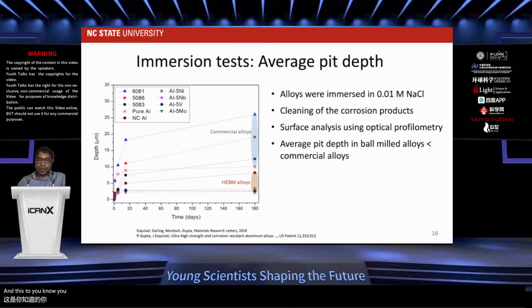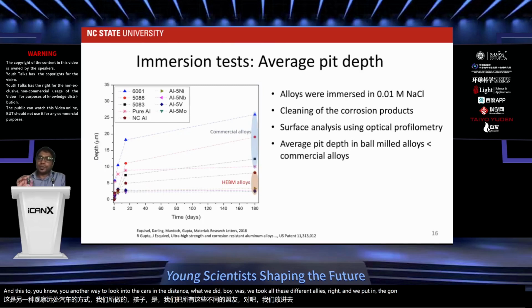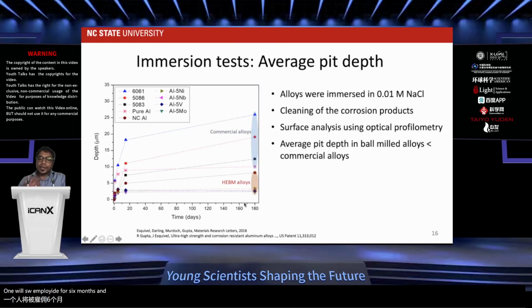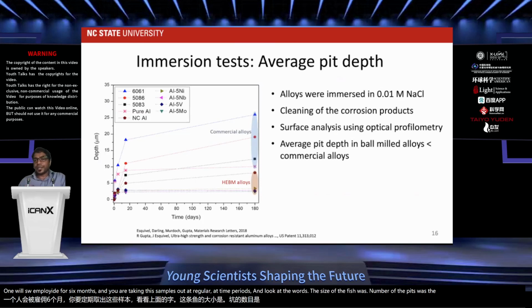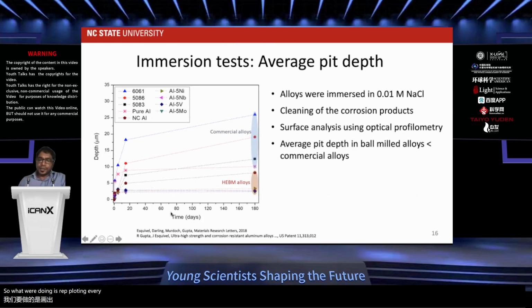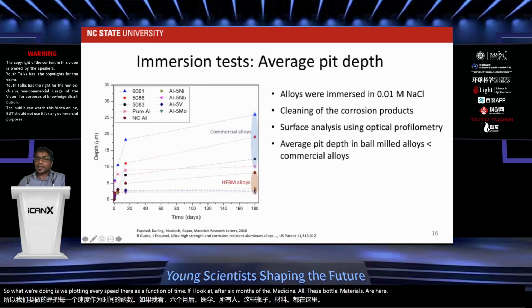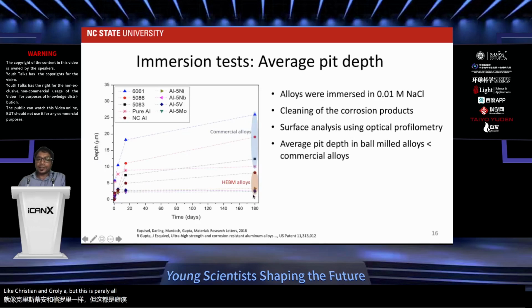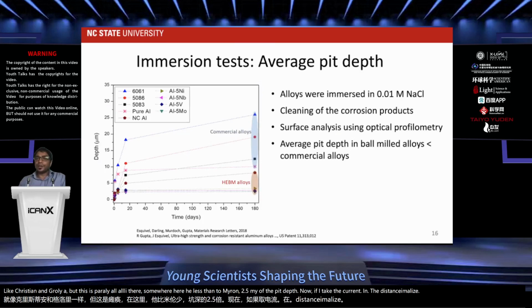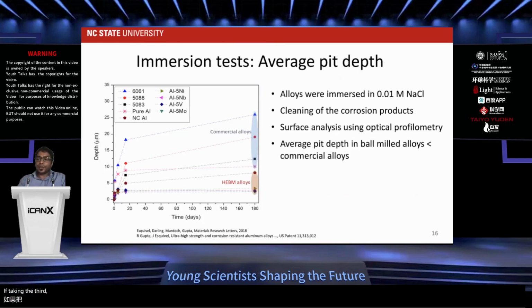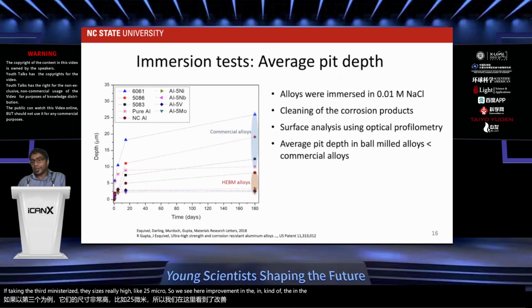And just to give you another way to look at the corrosion resistance, we took all these different alloys and put them in the 0.01 molar sodium chloride for 6 months. You take these samples out at regular time periods and look at the size of the pits, the number of the pits, the pit depth, maximum pit depth, average pit depth. So we're plotting average pit depth as a function of time. If I look at after 6 months of immersion, all these ball milled materials are here. Pits didn't grow very much. This is pure aluminum. All the alloys are somewhere here. It is less than 2 or 2.5 microns of pit depth. Now, if I take the corrosion resistant aluminum alloys, I'm not talking about high strength like 7075, their pit size is really high, like 25 microns. So we see a huge improvement in the pitting corrosion resistance.